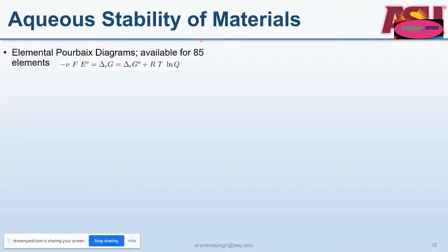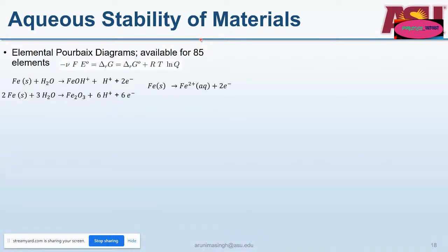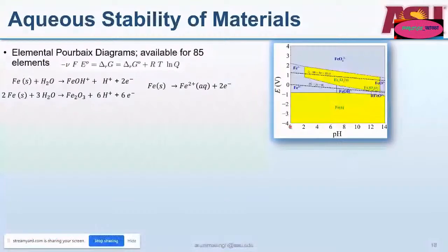Let's assume that something is iron. So if you put iron in water, these are some of the possible reactions which could happen. You put iron in water, it could form a hydroxide. It could form an oxide, or it could just form these aqueous Fe2+ species and corrode. And which one of these reactions is actually stable? You can determine that using the Nernst equation, which gives you the relation between the chemical and the electrical driving force. And if you know the reaction energies of each one of these reactions, and you know what pH you're at, which is basically the concentration of hydrogen ions, and the potential you're at, you can generate these so-called Pourbaix diagrams, which give you the stability region of different species as a function of pH and potential, which are possible for a specific system when it's placed in water.